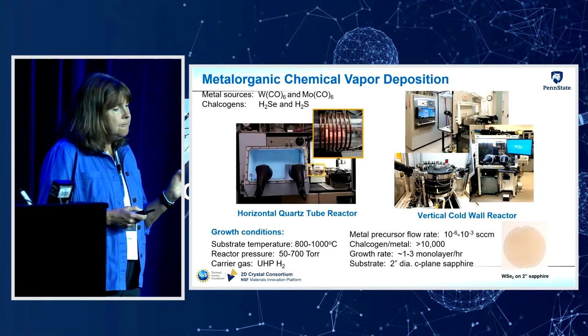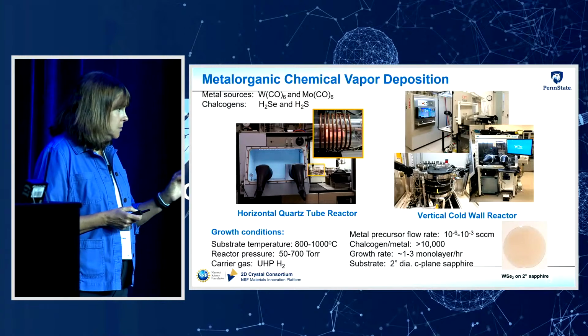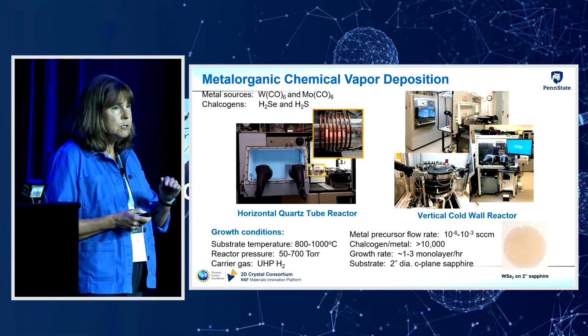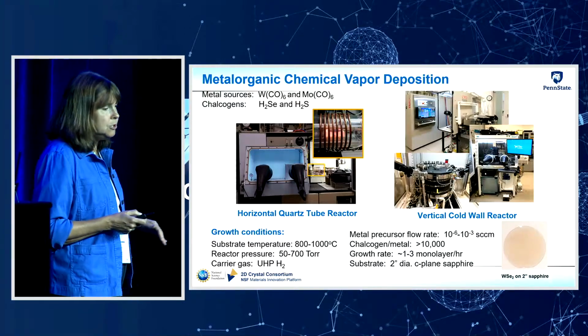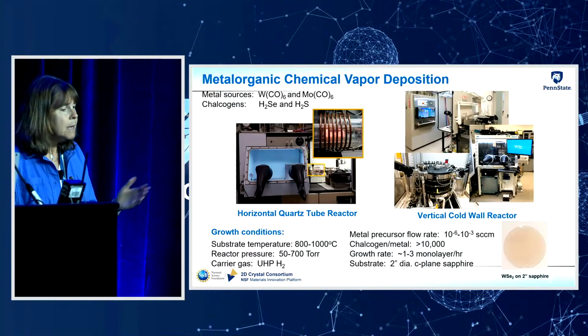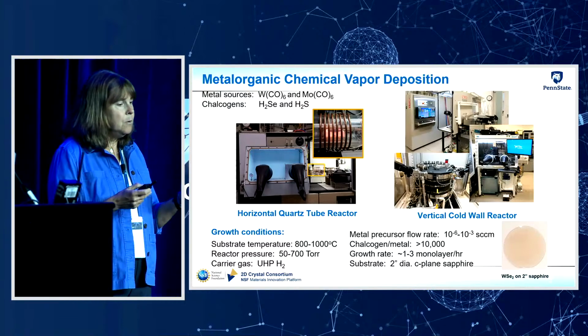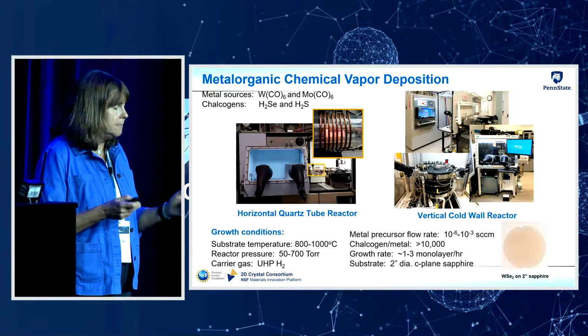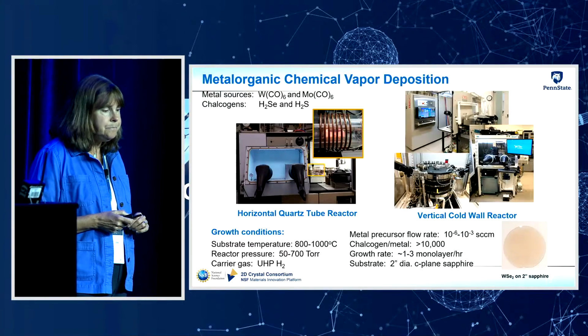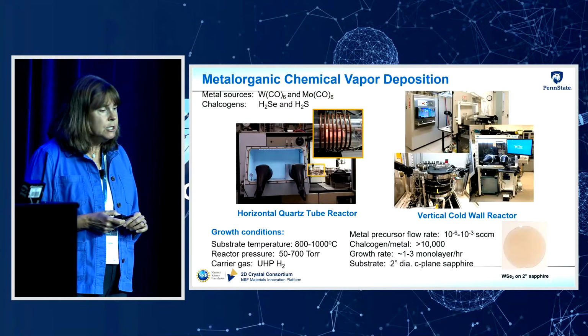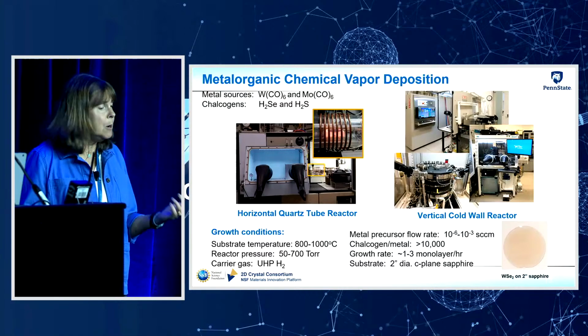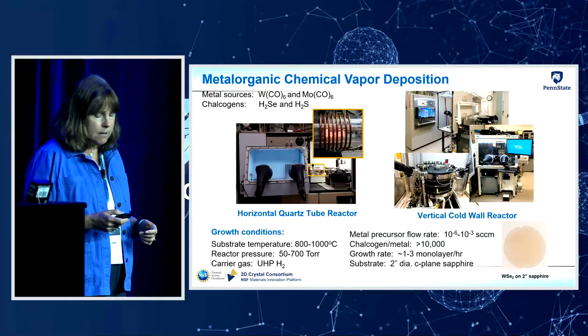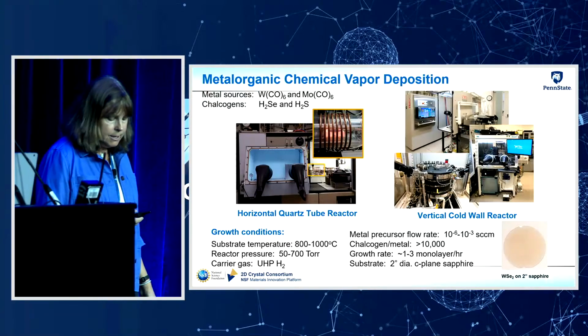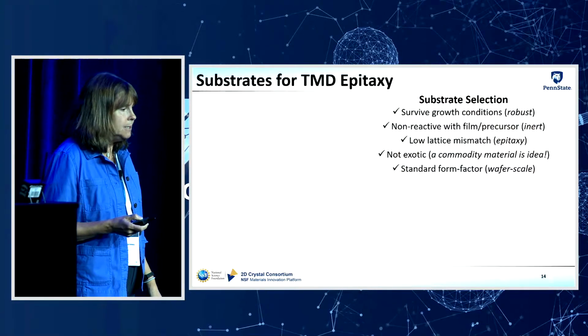We use a very low flow rate of the metal precursor. That is what controls the growth rate. And as I mentioned, we want to grow very slowly, so we just get a single monolayer. But then we have to use a high chalcogen to metal ratio because of the differences in the sticking coefficient. And using those conditions, we have growth rates on the order of about 1 to 3 monolayers per hour. And as I mentioned, we grow on 2-inch diameter sapphire substrates.